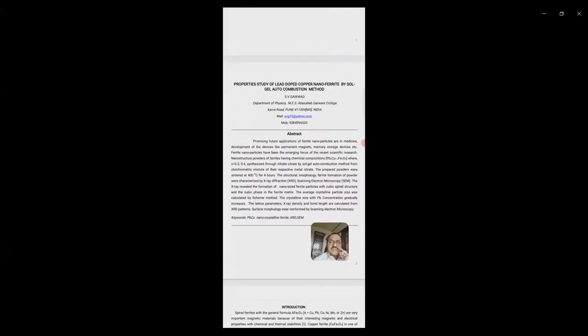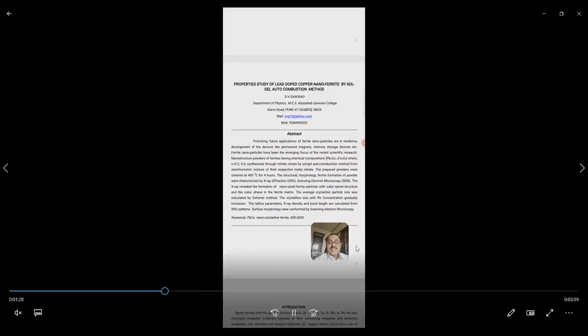This is the abstract of my paper, where I have prepared lead-doped copper nanoferrite by the sol-gel autocombustion method. That lead-doped copper nanoferrite has a number of applications in memory storage devices, sensors, etc. Here I prepared the nanocrystalline composition Pb(x)Cu(1-x)Fe2O4, where x equals 0.2, 0.4, 0.6, synthesized through nitrate-citrate by the sol-gel autocombustion method from a stoichiometric mixture of the respective metal nitrates. The prepared powders were sintered at 400 degrees centigrade for 4 hours.